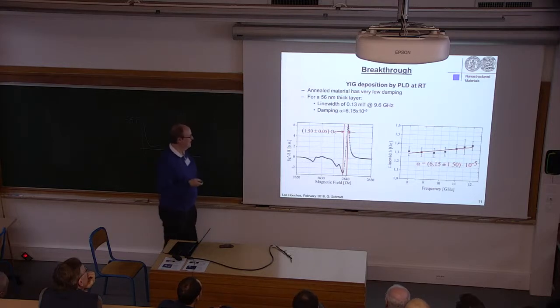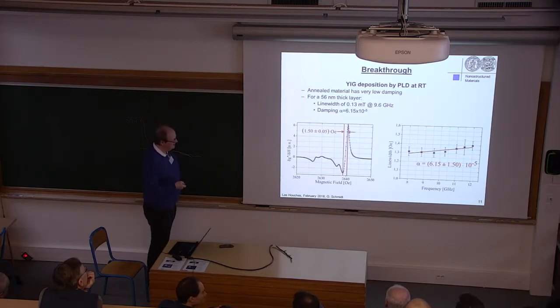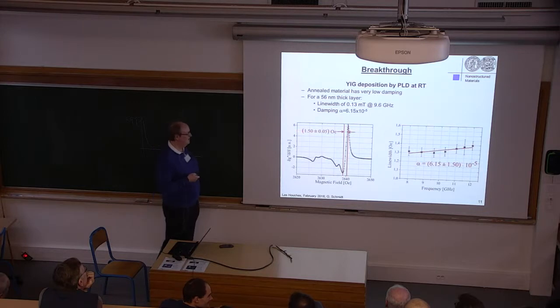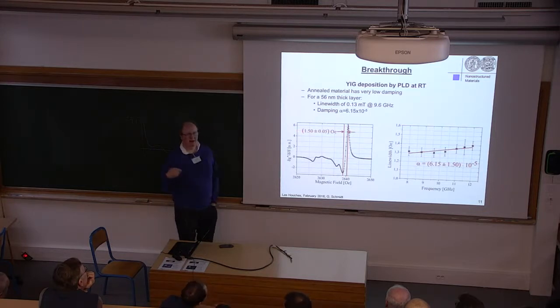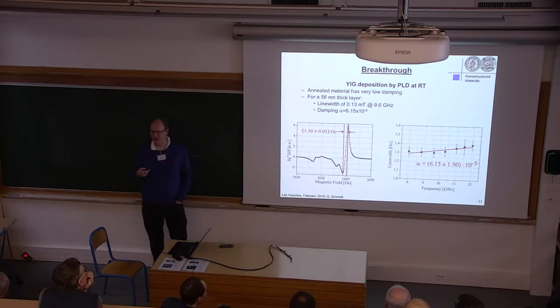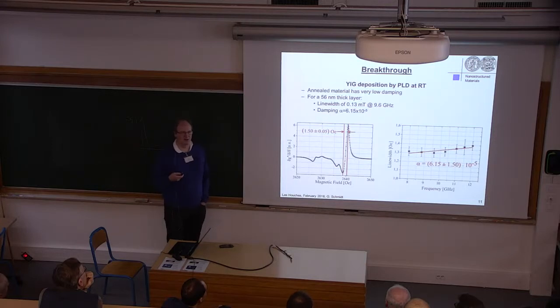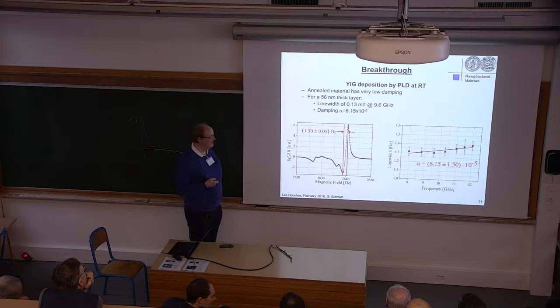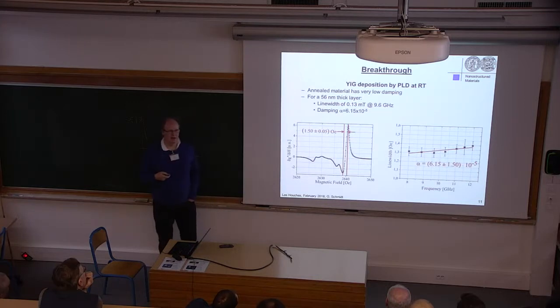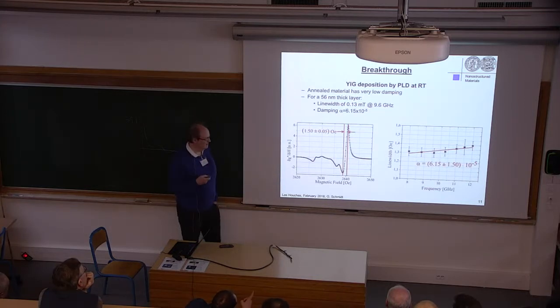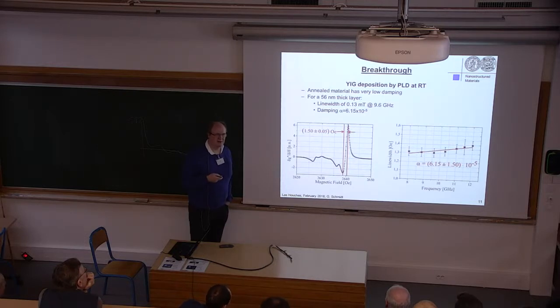And in this case, what we found, we have a line width, so this is the measured line width from the diagram, of 1.5 Oersted. So this translates to 1.3 Oersted line width at 9.6 gigahertz. So this is already very small. It's among the smallest values published for thin layers. And the damping is 6 times 10 to the minus 5, which is the lowest value published for thin films. We don't know why it works, but it works.